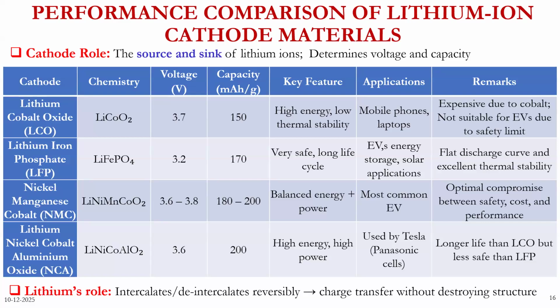Next is nickel manganese cobalt, NMC batteries, and this is one more advanced technology of battery. Lithium nickel cobalt aluminum, we call it NCA batteries. Almost all the batteries have a similar voltage rating of around 3.2 to 3.8 volts. If we clearly observe the milliampere hour capacity per gram, to keep it in very simple words, 150 mAh of capacity can be stored in 1 gram, just as an example. So every gram can hold only 150 mAh of battery capacity.